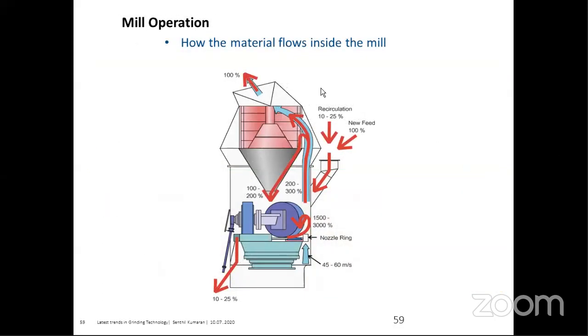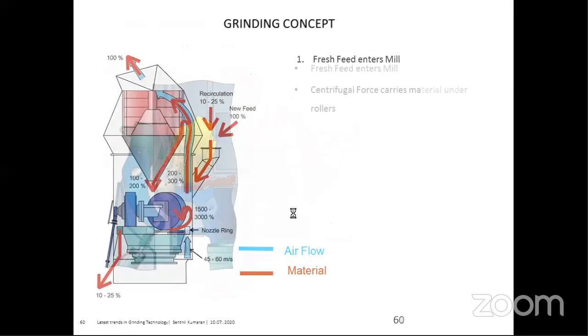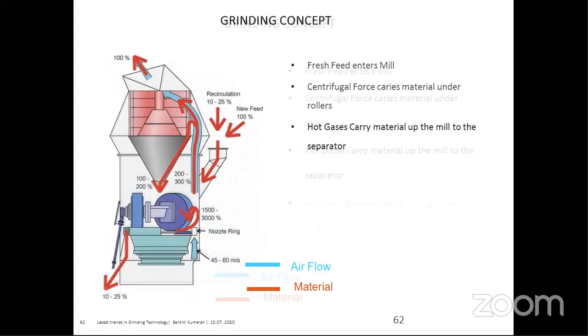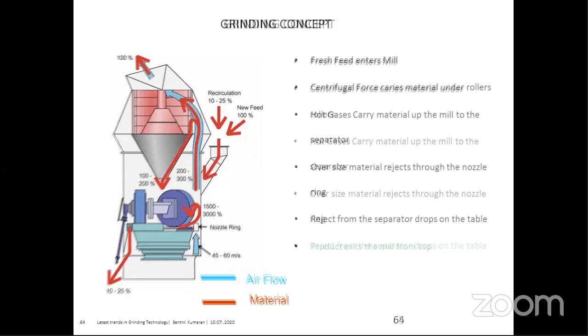So this is how the mill operates. The new feed enters the mill and goes to the table. It grinds well, and then some particles, 10 to 25% of the material, escape above the dam ring and go to the recirculation. The finely ground material goes to the separator, the fine product goes to the cyclones, and the coarse product is returned for recirculation. So this is how the mill operation is. We have seen this in the video as well.